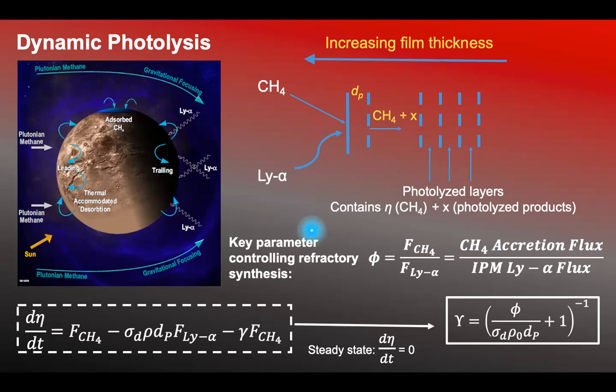All right. And a key parameter controlling this refractory synthesis is described by this relation here. This relation again talks about the concentration of the photolyzed methane in that layer. So that's the derivative of eta over time. And you have the incoming flux of the methane. From that, you have the Lyman alpha photolyzed portion described there, and then the portion here that's the fraction buried away in the layering process. So the key parameter controlling this refractory synthesis, assuming a steady state, meaning that this is essentially equal to 0, is the phi value here. And again, that's the ratio of the methane accretion flux to the interplanetary medium Lyman alpha flux.